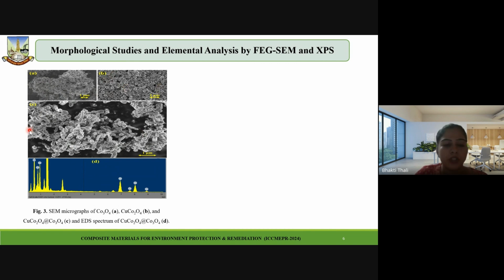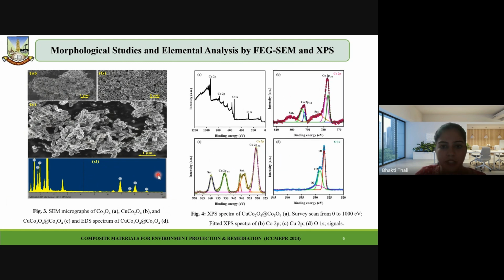And for the final nanocomposite, that is Figure 3C, we can see spherical particles along with rod-shaped morphology. In the EDAX spectrum, cobalt, copper, and oxygen are well present, which suggests that the formation of copper cobaltite cobalt oxide nanocomposite has taken place.